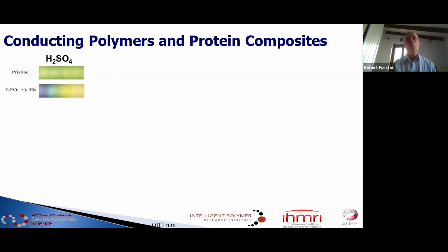If you then poise one of the feeder electrodes negative on this end, it induces a positive potential at this end of the bipolar electrode. You get oxidation of the conducting PANI polymer on this end, while the other end remains in the reduced state. If you change the polarity, you can cause the other end of the bipolar electrode to become oxidized instead. So we can control which end of the bipolar film is actually oxidized. And when you remove the feeder potentials, you again recover the state you had at the beginning.